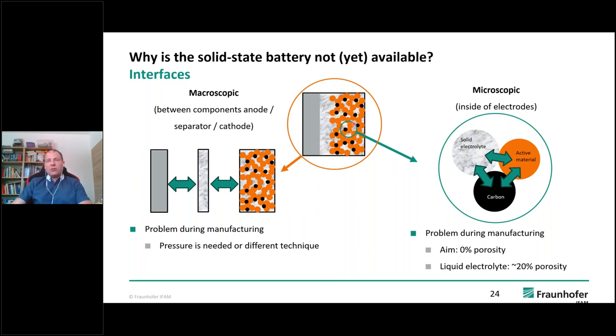And on the other hand, as I already somewhat told, in the composite cathode we have three components: the solid electrolyte, the active material, and the carbon. And you can see that when we make them round, we get these holes. The holes are dead material that we cannot use, and they make it harder for the transport processes to take part.